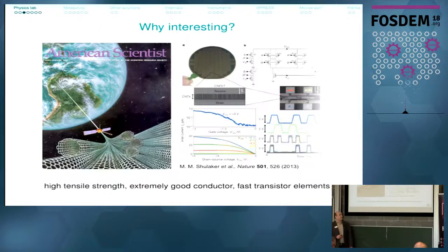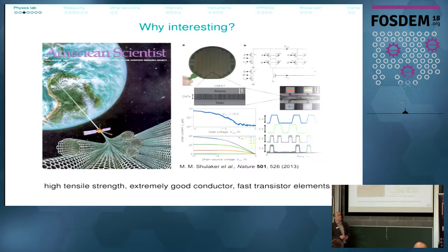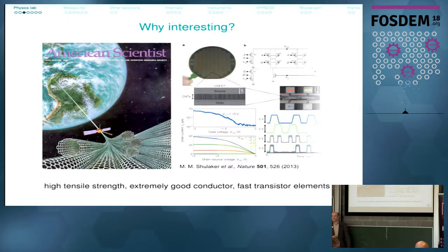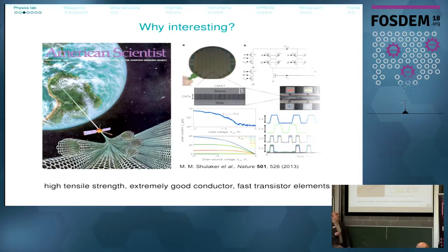Why is this interesting? They are very light and mechanically very stable — very tension resistant. This is more or less the only material where the numbers are right for building a hypothetical space elevator: you need something strong enough to carry its own weight over such a long length. On the other side, it's a very good electrical conductor. People have been thinking about using it for chip vias and very fast transistor elements. This is the first nanotube computer that was built — still far below anything x86-like, but the logic is essentially working.